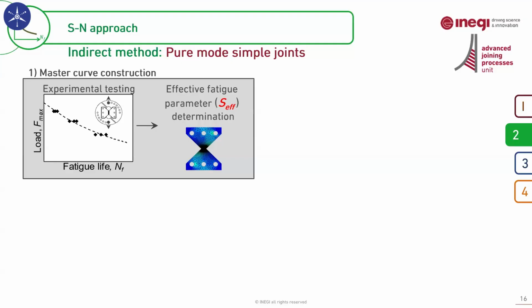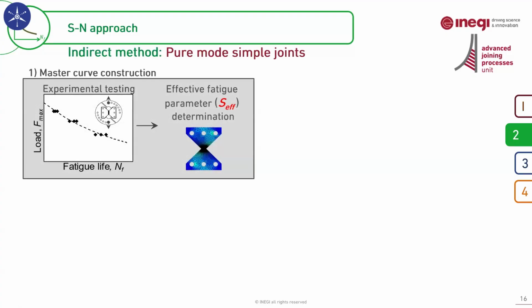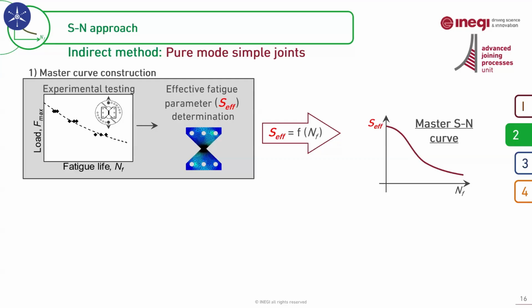It can be as challenging as a 3 years PhD project. And that's one of the most challenging parts of the indirect method. So despite the relatively simple test that we can perform in this method, the post-processing part is very challenging. But as long as we have this S-effective developed, then we are able to construct a master SN curve.